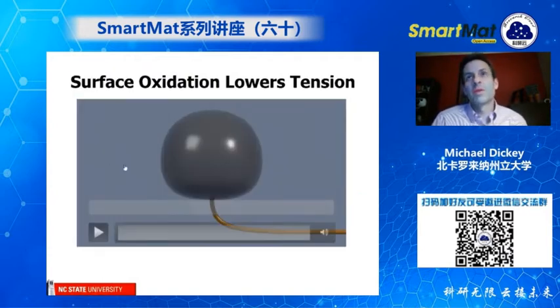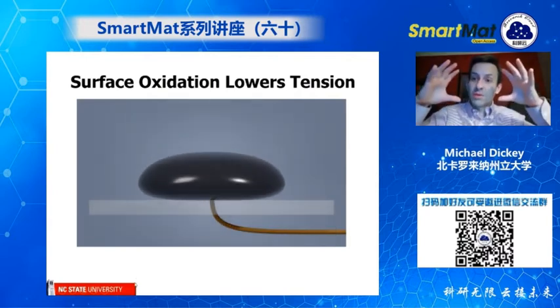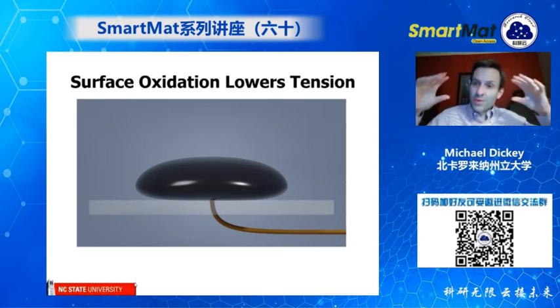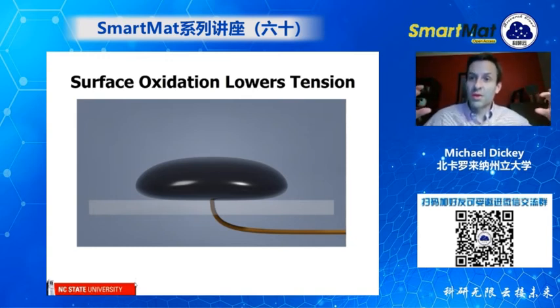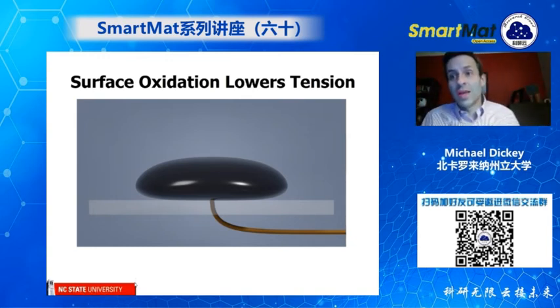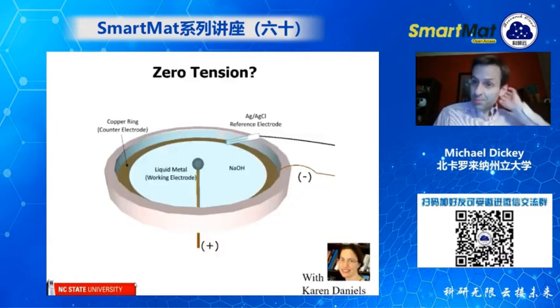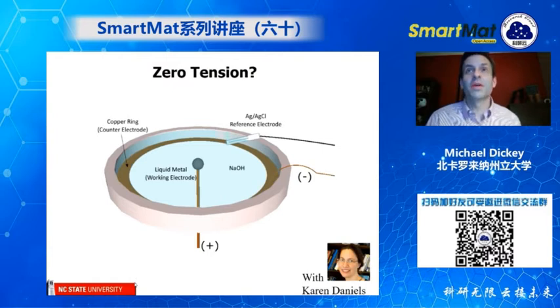So we did some experiments, and the experiment again consists of a little wire connected to the droplets, and we apply a voltage. And when you apply the voltage, the surface tension gets lower and gravity causes the metal to squish down. We use this to characterize the surface tension, and actually we found at just the right conditions, it looks like the surface tension is 0. Now, if a surface tension is 0, there should be no penalty for it to form additional surface area.